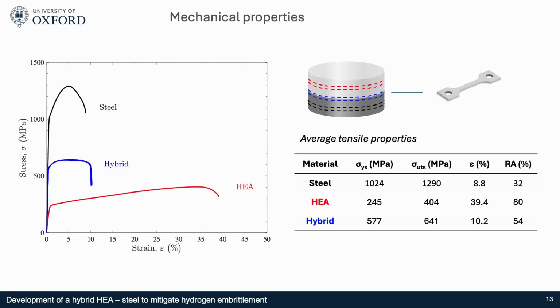And here we can see there are two experimental curves. So the scatter is very low. Both curves were similar, and the mechanical behavior is intermediate between the two materials. So we obtained a yield strength of almost 600 and an elongation of 10%. So we can say that we have obtained a material that is a little bit harder than the high entropy alloy and can provide this barrier for the diffusion of hydrogen.